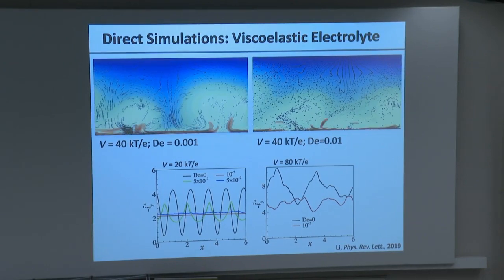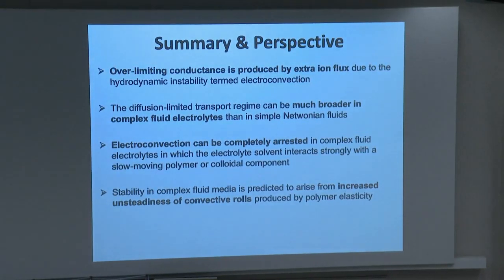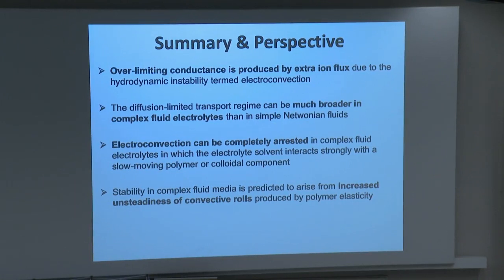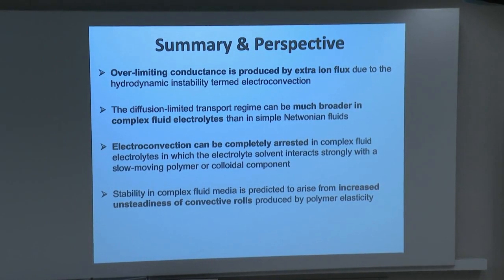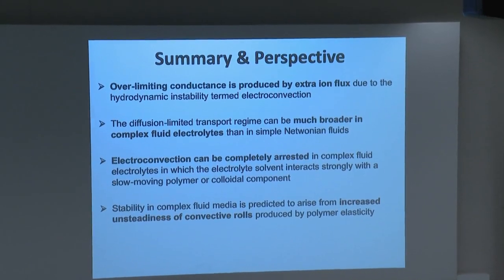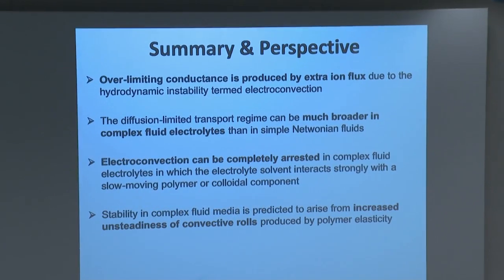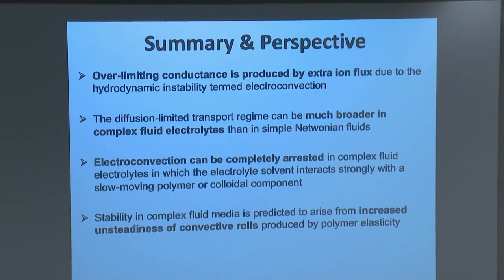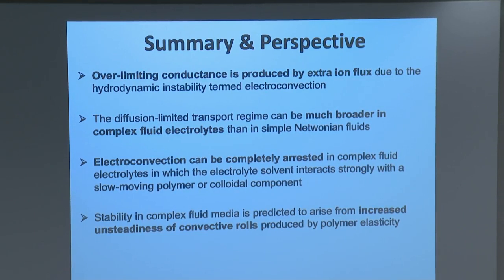All right, so the lessons from this part of the talk are actually pretty simple, but pretty important. The first lesson is that overlimiting conductance, this upturn in the IV curve, is in fact produced by convection. And what is important is that we can extend the diffusion-limited regime by using polymers that provide viscoelasticity in a liquid electrolyte. And perhaps more important is that if we arrest that convective instability, we can arrest the dendritic deposition of the metal, with the idea that we introduce unsteadiness in the flow that makes the deposition more uniform. So that is part A.